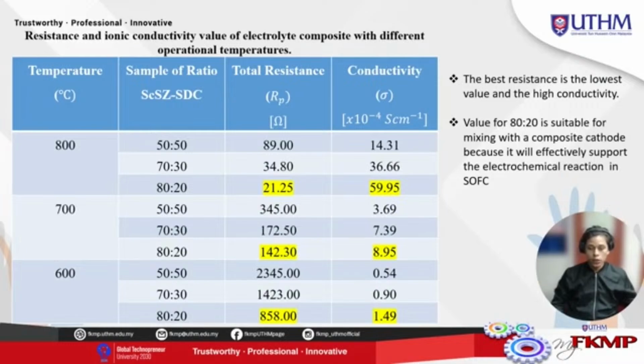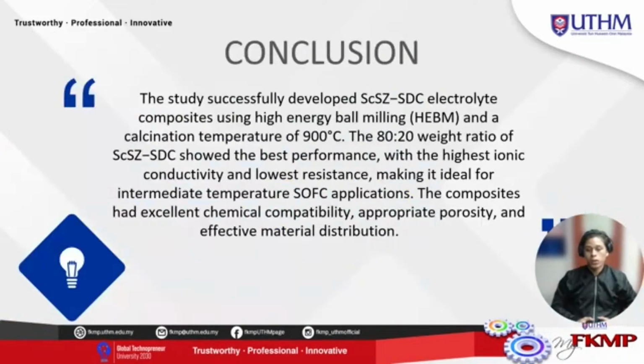The 80-20 is very suitable for mixing with the composite cathode, because it will effectively support the electrochemical reaction in SOFC. In conclusion, the study successfully developed ScSZ-SDC electrolyte composite using high energy ball milling and a calcine temperature at 900 degrees Celsius. The 80-20 weight ratio of the ScSZ-SDC showed the best performance with high ionic conductivity and the lowest resistance, making it ideal for intermediate temperature SOFC application. The composite had excellent chemical compatibility, appropriate porosity, and effective material distribution.